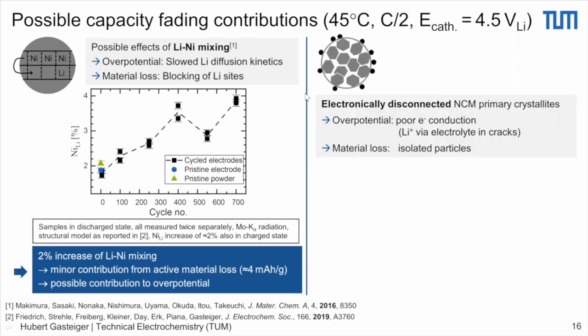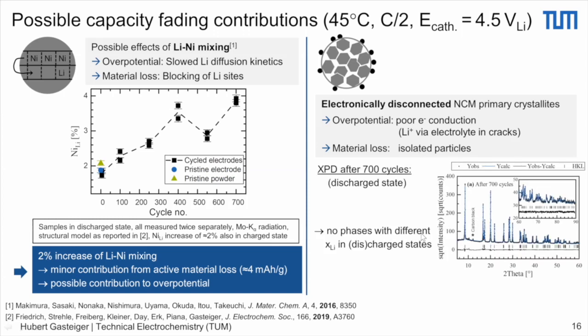The other thing is the cracking of the material. As we had seen, the material will crack over cycling, and it is possible that we get electronically disconnected materials inside the secondary agglomerate, where we have poor electron conduction, but of course a very good lithium ion conduction through the electrolyte in the cracks. And this would result in a material loss from these isolated particles. However, if that were to happen, what you would expect is that somewhere in the charged or in the discharge state, you would have to see materials which have different lithium contents. So layered materials, which have different lithium content.